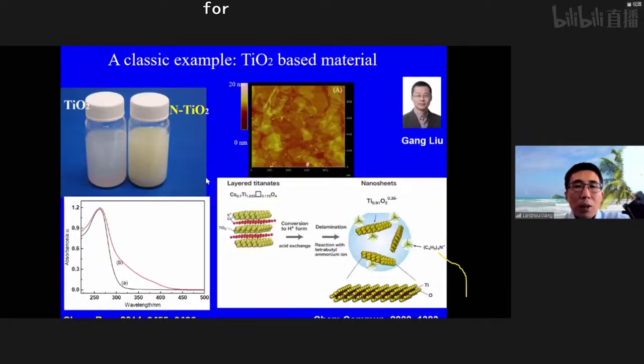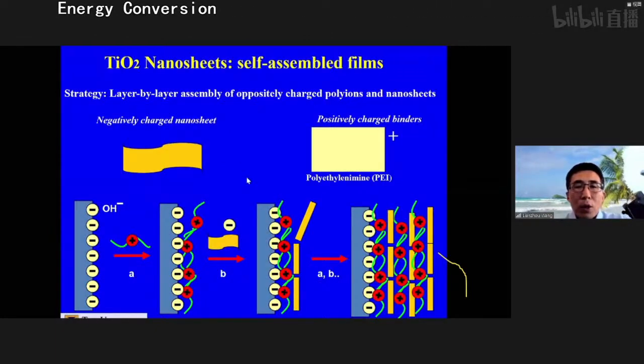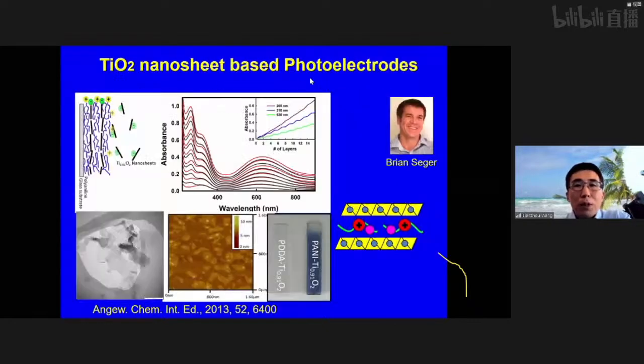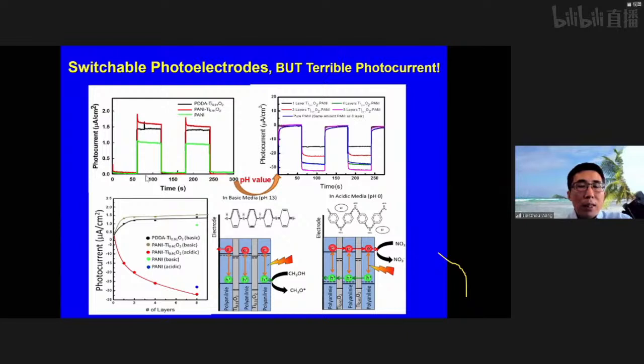So we started with some classic TiO2-based material, because in the photocatalytic area, this is, I think, the most studied material. We started with a layered compound for the TiO2, and delaminated it into nanosheets of TiO2, a single layer, and we used this to assemble the electrode layer by layer and tried to test the performance of the TiO2-based photoelectrode. For example, in this one we used layer by layer in combination with some polyaniline as the binder. But unfortunately, we found that the photocurrent generated on this TiO2-based electrode is terrible.